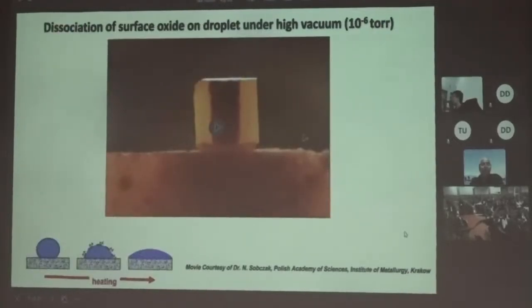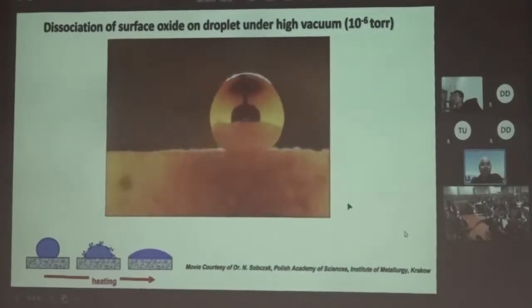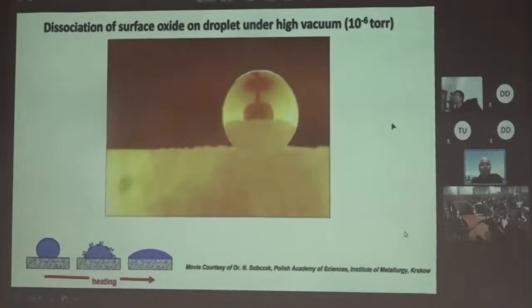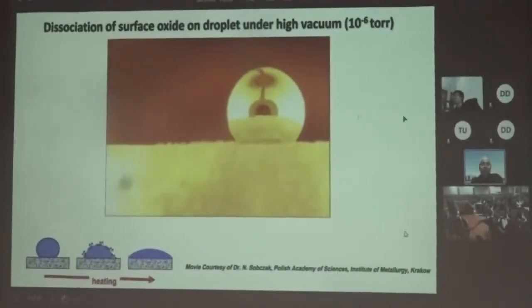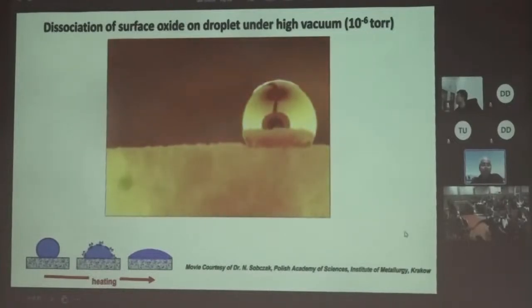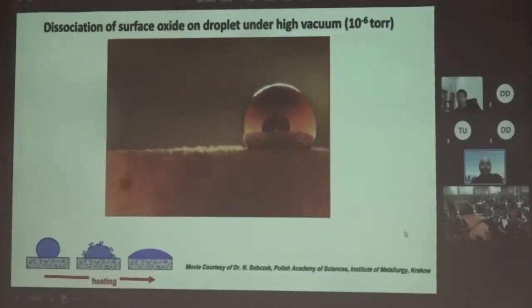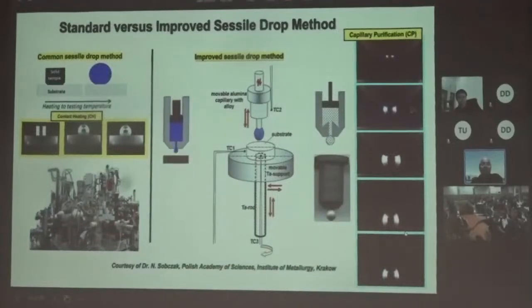Well, let's look at another example here. You're looking at how at high temperature the oxide will actually disintegrate. You can see the little particles of oxide broke off and you have a cleaner surface here. And this is because, not just because of high vacuum, even under this vacuum you will have an oxide skin, but the temperature was increased above 1000 Celsius. So there was oxide dissociation. So how do you handle some of these problems?